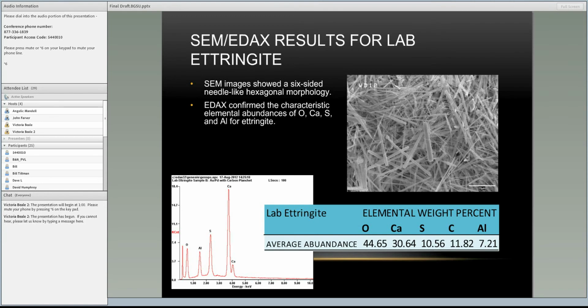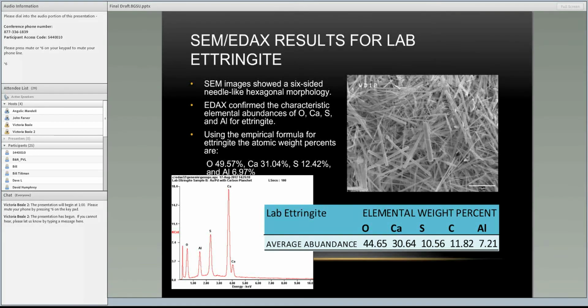This is the result we got from the SEM. We took the empirical formula of ettringite and calculated the atomic weight percents for each element. If you compare those, oxygen should be about 50%, and we're very close to that. Calcium, very close, in the 30s. Sulfur, around 12; this one was close to 11. And aluminum, 6.97% versus 7.21%. So our results were actually very good. We were very close to the actual atomic weights going from the formula.